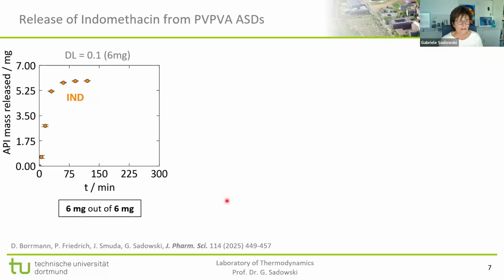It gets even worse if we do not look at the relative release, but at the absolute amount of API released. So that's an experiment where the drug load is 0.1, and that means that, for the particular size of the tablet, we had a sample that contained 6 milligram of indomethacin. At the drug load 0.1, you can imagine the tablet was quite small. The other 90% is the polymer, and the indomethacin total absolute amount is 6 milligram.